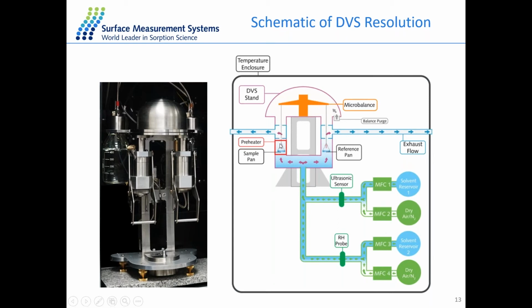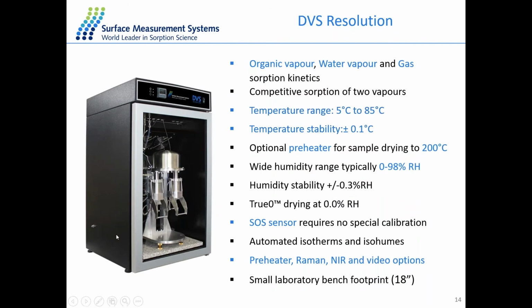The sample inside the chamber here will pick up the moisture, and the mass change will be recorded by the balance. The whole stand, like this one, will be set in an incubator with a temperature range from 5 to 85 degrees. That means we can perform the experiment anywhere from 5 to 85 degrees. But in some cases, we might need to precondition the sample at higher temperature, and in that case, we can install a preheater under the sample chamber at this location. This will allow you to precondition the sample in situ before the experiment, up to 200 degrees.